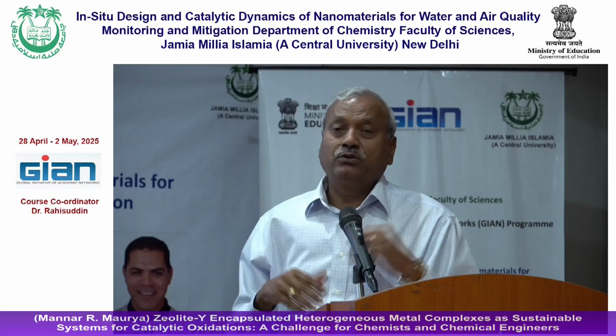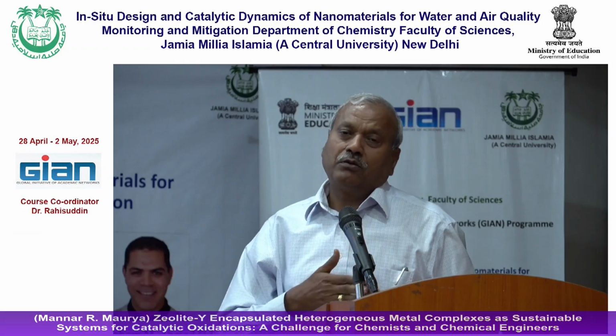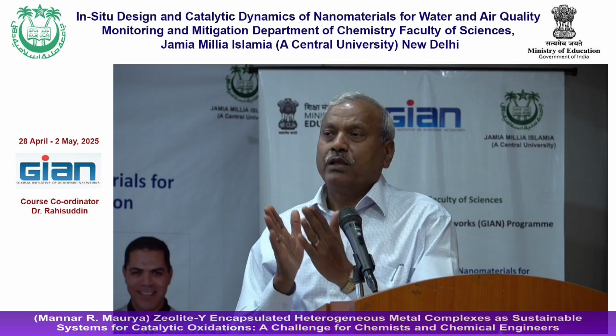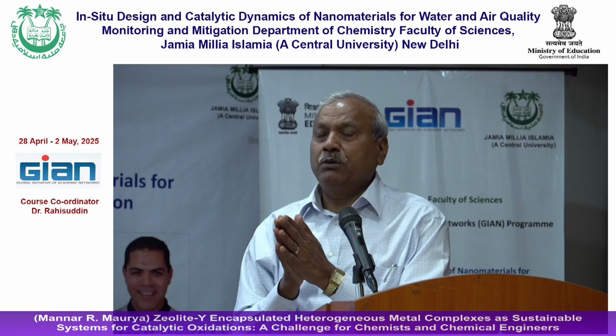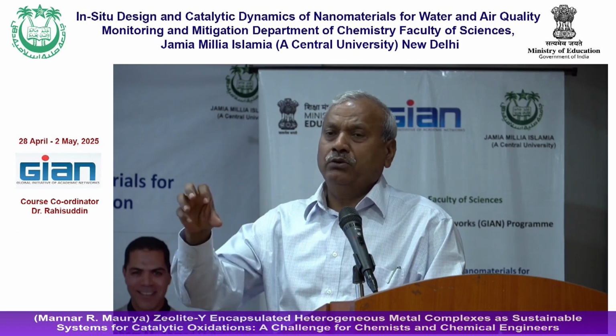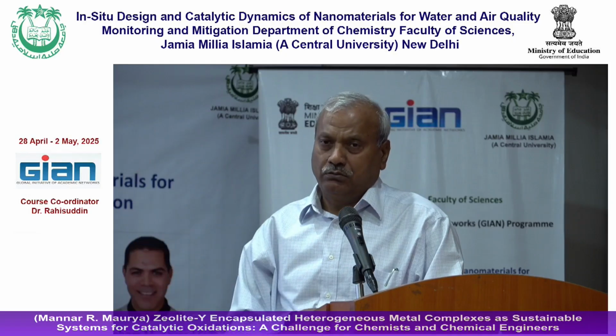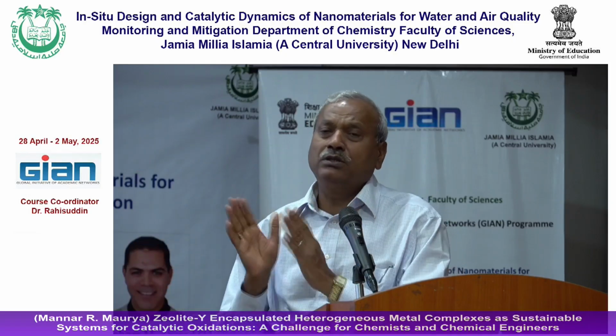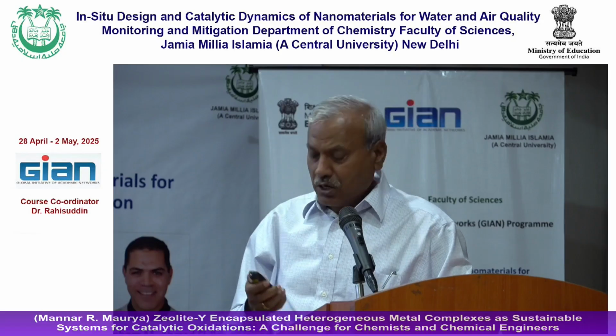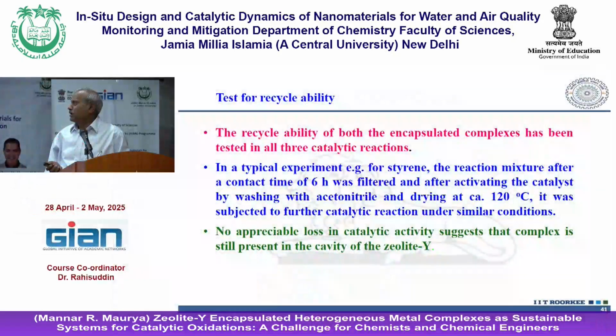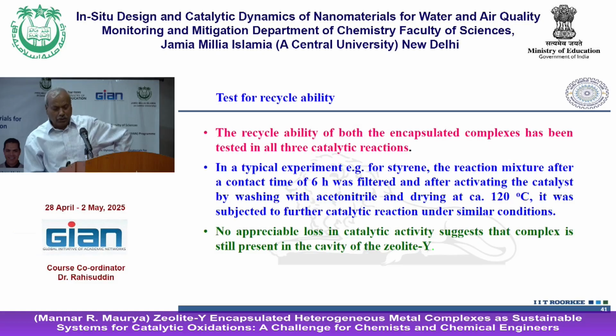The other way we have also done: separate the product from the reaction mixture, wash the zeolite encapsulated complex with acetonitrile, dry at 120 degrees, and do the further reaction. Taking the same amount, it gives almost the same product, the same conversion. It means the catalyst is very stable and not reacting. Okay, so we have moved further.